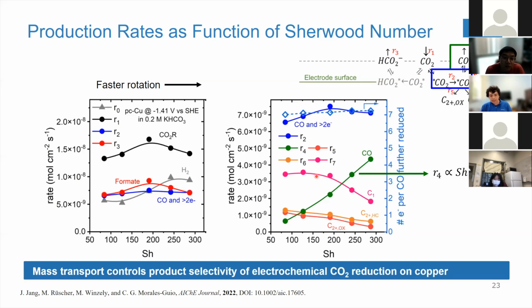So with this, we want to emphasize this is the same driving force, the same applied potential. When we change the mass transport, we change the mass transport properties far away from the double layer. We're not affecting the double layer in any way when we increase the rotation, because we're not modifying the potential drop at the interface. We're only affecting mass transport properties maybe 10, 100 nanometers away from the surface of the electrode. And that is actually enough to explain these changes in CO2 selectivity.